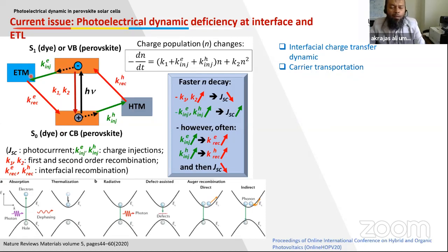and the electron will be injected to the ETM. The nature of the charge transfer here also strongly depends on the surface properties of the perovskite and the surface properties of the ETM or ETL, and the nature of coupling between these two materials, as well as the band alignment of these two materials. So when the charge transfer does not occur easily, electron carriers may accumulate at the surface of the perovskite, then it will again trigger radiative band-to-band transition or defect-assisted recombination.